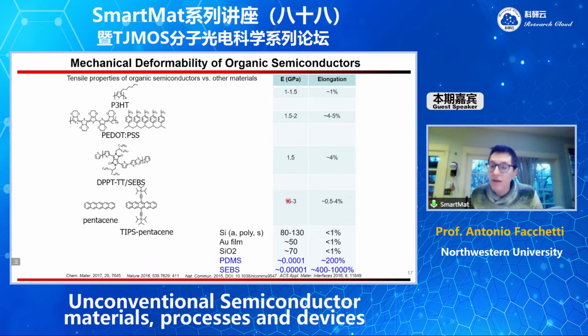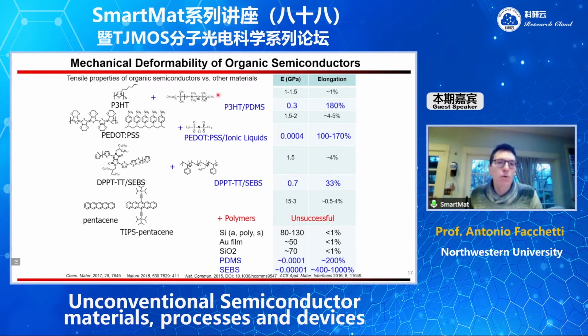So you want to have a Young modulus which is very, very small, and an elongation at break which is very, very large, okay? And if you compare these numbers with typical electronic inorganic materials, the Young modulus indeed is much smaller and the elongation at break is larger. But if you compare the numbers with the real elastomers, like PDMS or SEBS, these are large and these are small. So what the community has done is to improve these numbers by blending, and you can blend P3HT with different types of PDMS, put in an ionic liquid, put in some elastomers, and you see here that there is a depression of the Young modulus and an increase in the elongation at break, which is a very successful strategy, works very well with polymers. And in many cases, this process also improved the performance of the semiconductor, so it's not always deleterious.